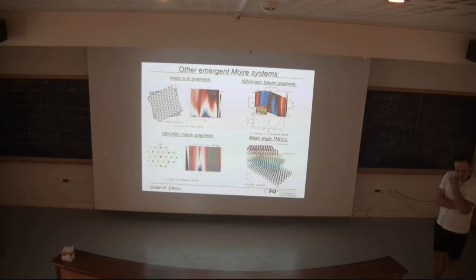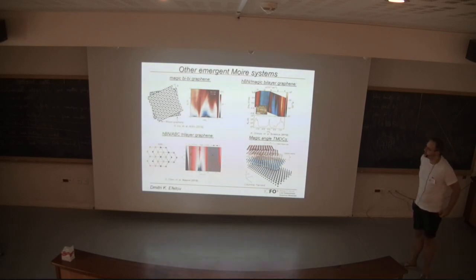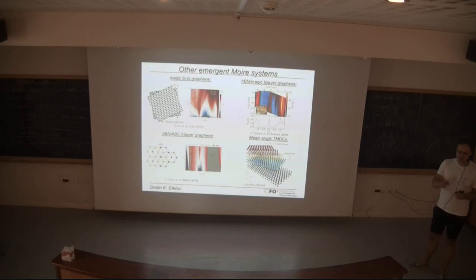For this stack by graphene, qualitatively, do the results improve in terms of measurable quantities? There are several improvements. It's actually easier to get a magic angle in these. You don't have to align it to 0.1 degrees precision, but now with 0.2 degrees precision, so it's easier to get.